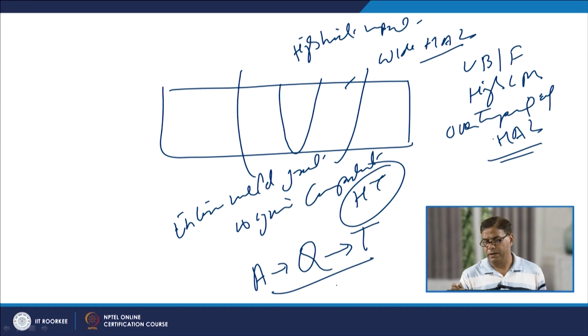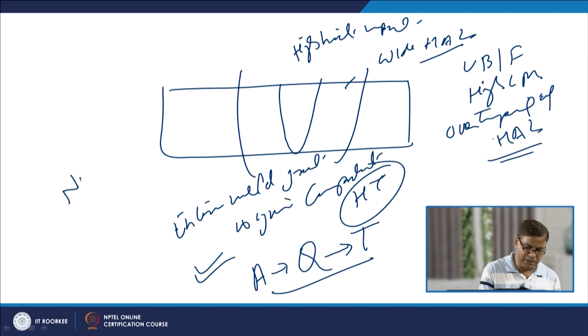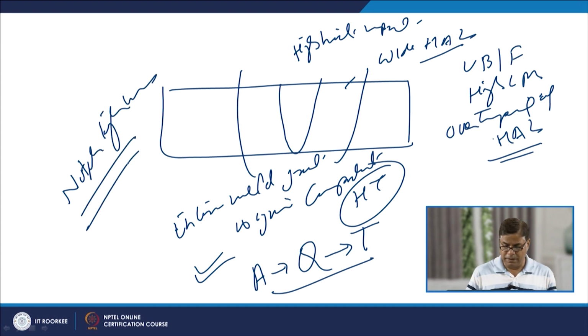So, the adverse effects related with the high heat input associated with the electroslag, electrogas, and submerged arc welding processes can be reduced. The complete heat treatment of such weld joints is needed, so that especially the notch toughness can be restored, apart from maintaining the required combination of the properties.